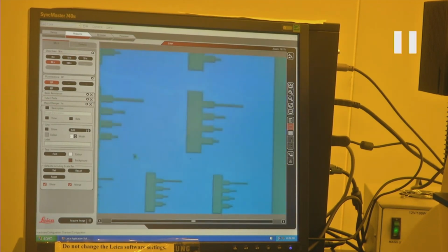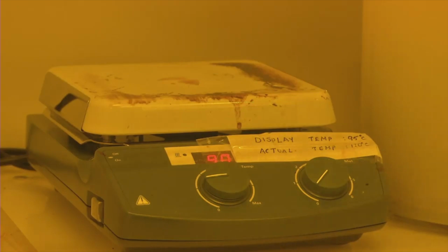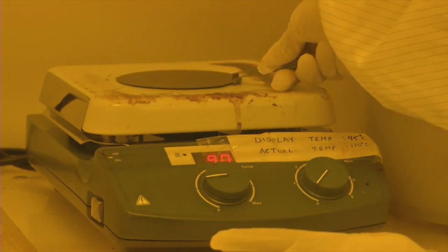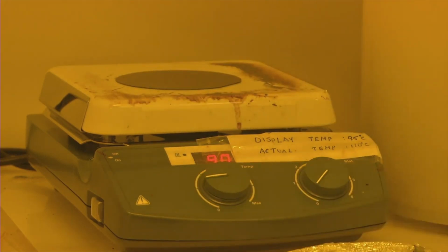What you see here in blue is the silicon nitride, and the lighter shade here is the photoresist, the photoresist of the pattern that we designed. This is the cantilever we would like to transfer the pattern to. So we are looking at whether there are any defects present on the mask or in the reproduced structure. After inspection, we do a post exposure bake, or hard bake.